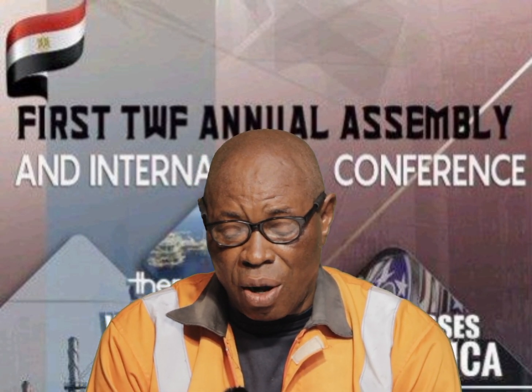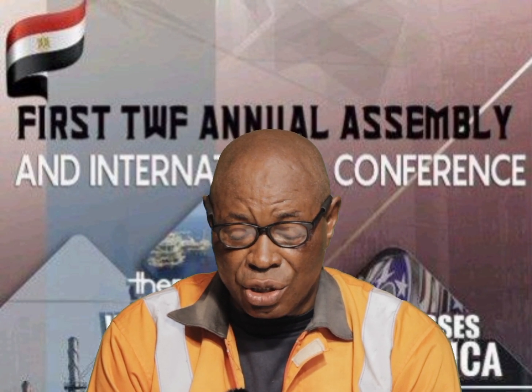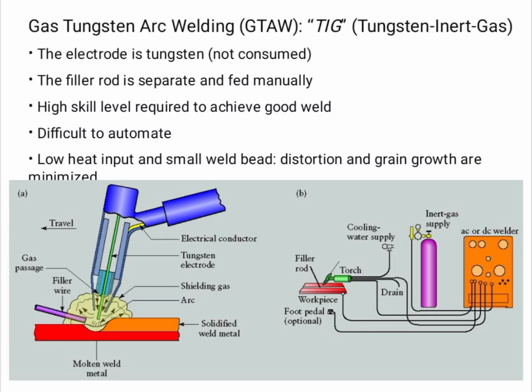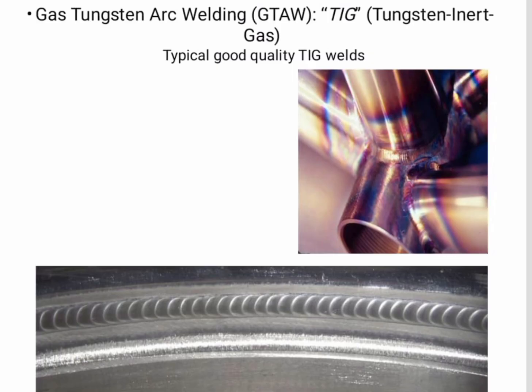TIG welding, which we also call GTAW, consists of an electrode called tungsten, which is not consumable, and the filler rod is separate and fed manually. A high skill level is required to achieve good welds, and it is difficult to automate. Low heat input, small weld bead, distortion and grain growth are also minimized. It consists of a welding torch and the inert gas supply, then an AC or DC welding machine, and the water drain and cooling water supply system. Welds done with TIG look good in appearance, and the few defects you can spot in a weld made by TIG depend on the skill of the welder.